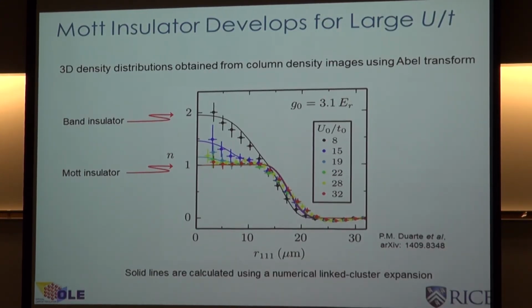All right, so once you get to low temperatures, then you can start looking for some of the interesting phases. These are density distributions that are obtained by doing something called the Abel transform on the column densities that we actually measure. So these are real three-dimensional densities. At relatively low interaction strength, we get a band insulator with this particular number of atoms. For a higher interaction strength, it gets closer and closer to a density of 1 at the center until finally, when we get to interaction strengths of between 20 and 30, we actually form a Mott insulator with a very flat region in here corresponding to the Mott plateau.